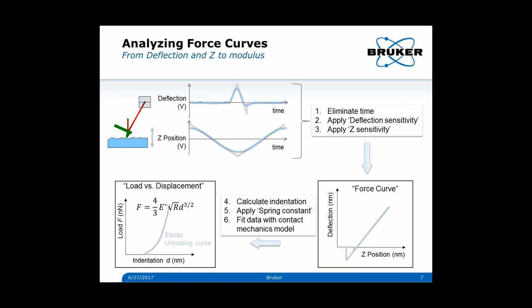Okay, in the case of peak force tapping or peak force QNM, the data is essentially the same except for one difference, and that is that the Z position is now not a linear ramp, it's a sinusoidal ramp, and that causes some curves. In other words, the maximum force is no longer going to be pointy. As a function of time, it'll be rounded off. But once you eliminate the time out of that, you'll still get a force curve that looks pretty much identical.